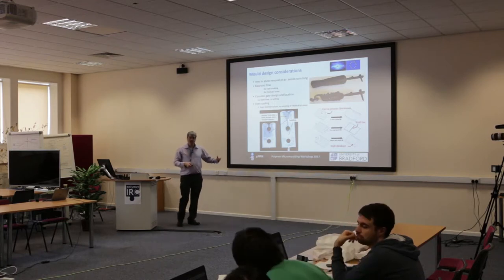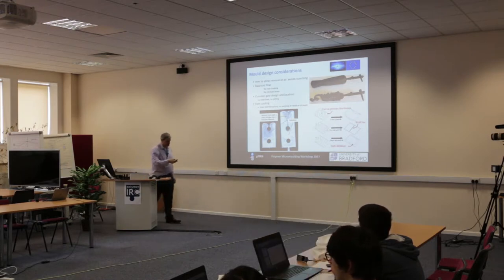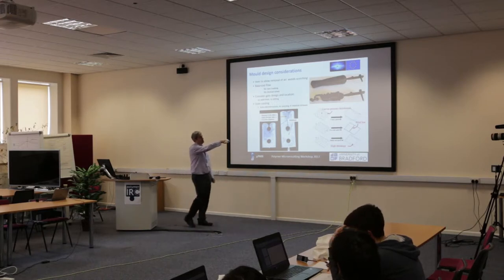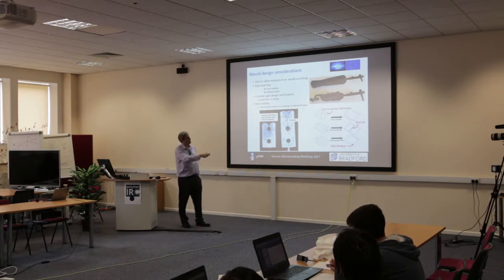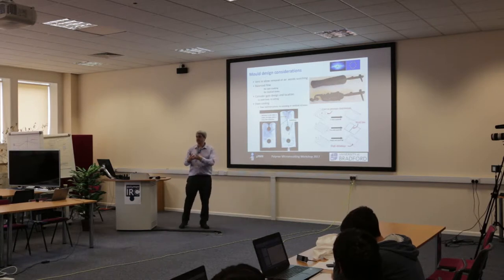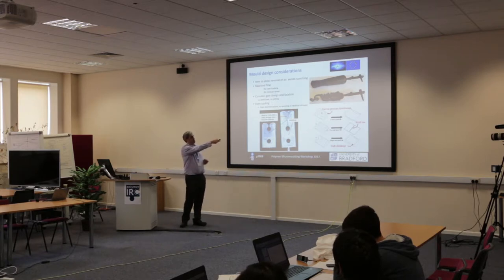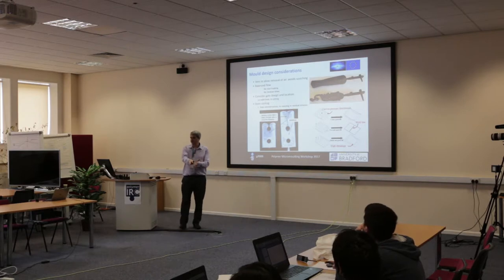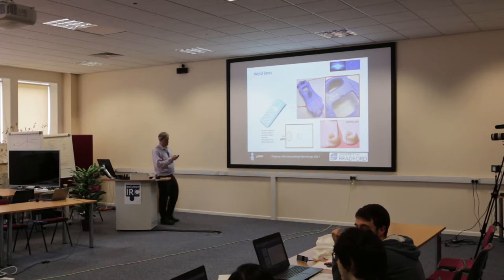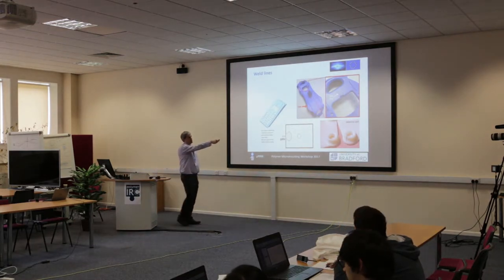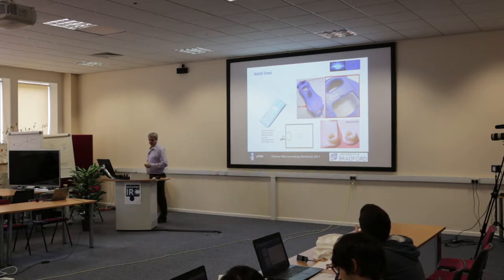In many cases weld lines can't be avoided — if there's a hole in a part, no gate location will prevent them. But we can use FE modeling to ensure weld lines don't fall on highly stressed regions. Gate size and location must also be chosen to avoid jetting behavior, particularly for fiber-filled materials. Rather than a nice uniform filling pattern, jetting causes the material to snake into the cavity, creating a mass of weld lines, poor surface quality with visible flow marks, and no benefit of shearing flow alignment — leading to random distribution and internal weaknesses.